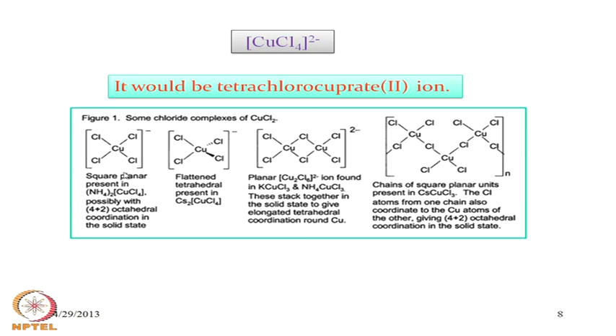So, we can get the corresponding networking or some supramolecular interaction between the CuCl4 2 minus species for chloride sharing, because whenever we have the corresponding crystal packing, we see that this is the anionic part. So, the cationic part will be coming in between two anionic parts. So, there are some void spaces, and void spaces would be occupied by the cations. But in this particular case, the size of the cation is very small, which is the ammonium ion. So, the void spaces are very small and do not inhibit the corresponding sharing from the adjacent molecule through its Cl.